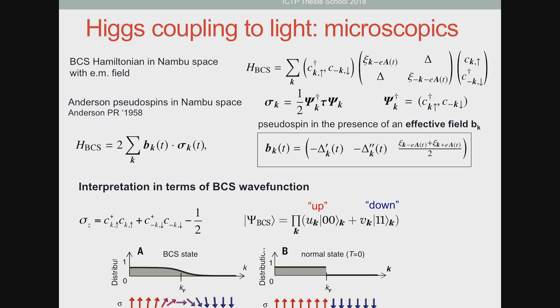So maybe the simplest is to start with a normal metal at T equals zero. When you are below kF, they are occupied, so you have spin one half. And when you are above kF, those are unoccupied, so you have spin minus one half. Now, in the superconducting state, you actually have a mix of these two states, so that the spins take orientations that are a combination of this plus one half, minus one half state.